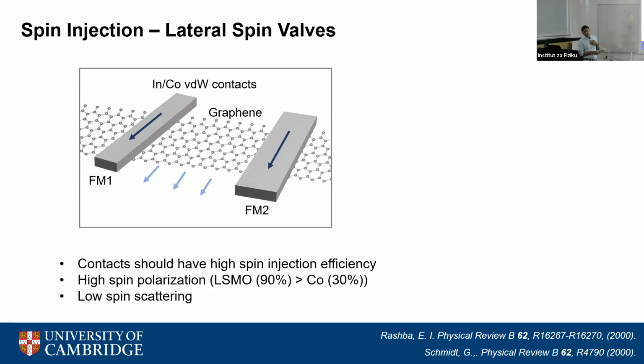Like I think iron is around 40%, nickel is around 28%, cobalt is somewhere in between, which means if you have 100 electrons, only 40 of them would be spin polarized. And when you introduce them, you want to ensure that most of the electrons which are introduced still remain spin polarized and are not scattered at this interface.